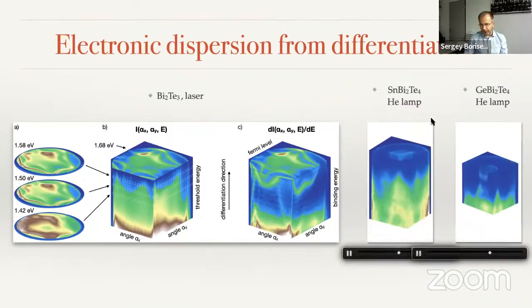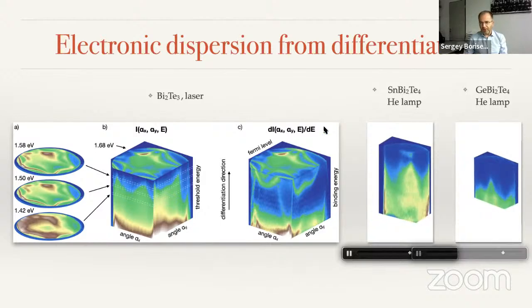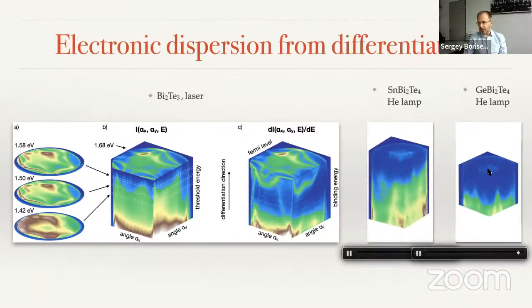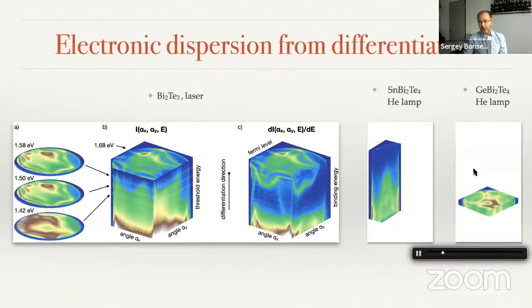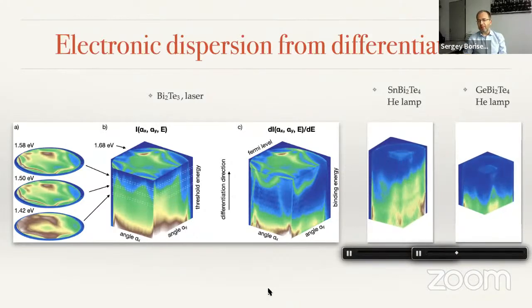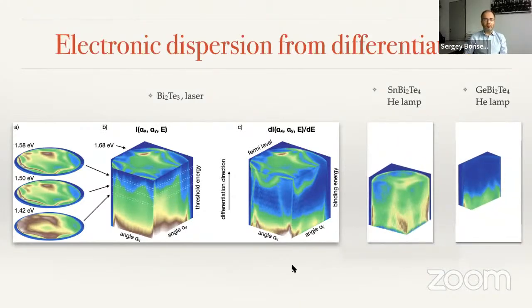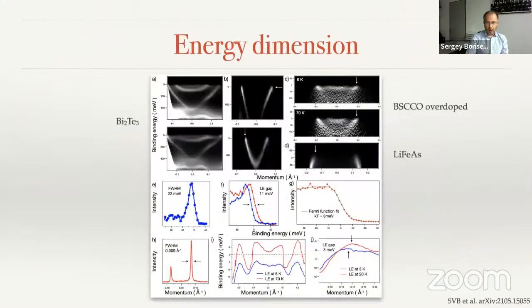So these are different topological materials where you could see the cones of the topological state, using actually a helium lamp in your lab so that you don't need to go to the synchrotron. The resolution in terms of energy is not a record one, but this is still pretty decent in order to see the opening of the superconducting gap.